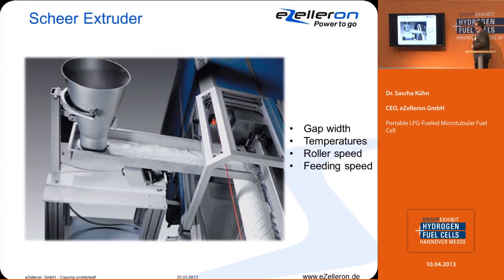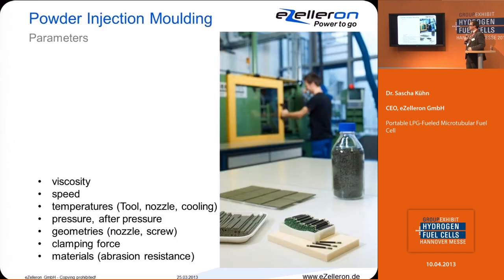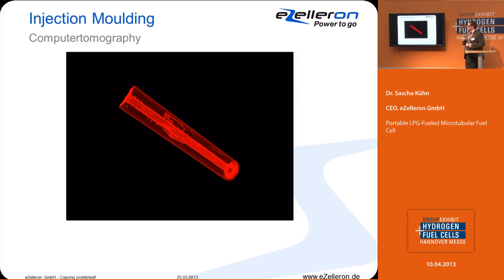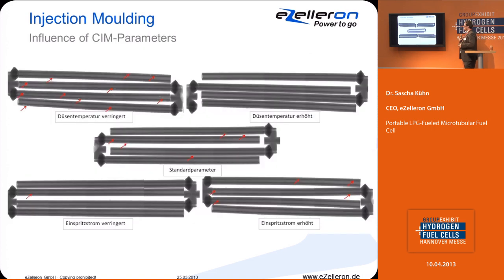The shear extruder is the first unit where the nano powders are compounded. So it's important to learn about all the parameters needed for the later production, like gap width, temperatures, roller speed, and feeding speed. During the powder injection molding, there are again a lot of parameters you have to learn about, and afterwards you have the first parts, which can be controlled, for example, by computer tomography. You see that in the beginning there were still a lot of failures in our parts which could not be seen from outside but were inside of the tubes. By using different injection molding parameters, we were able to improve that and to get rid of any failures.